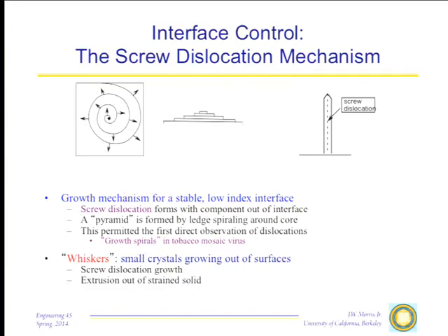If you can subsequently persuade that dislocation to climb out by heating it or something of the sort, this is a way of creating an absolutely perfect crystal. Not too big, but perfect. And many years ago, people discovered this and used it to do the first studies on crystals that you could assume, except for a few vacancies, were really, really perfect. No dislocations, perfect crystal. And these whiskers, this is still used as a method of generating some kinds of fibers.